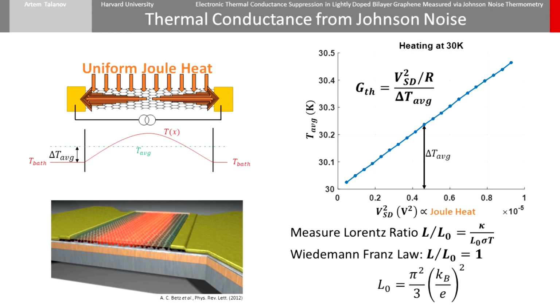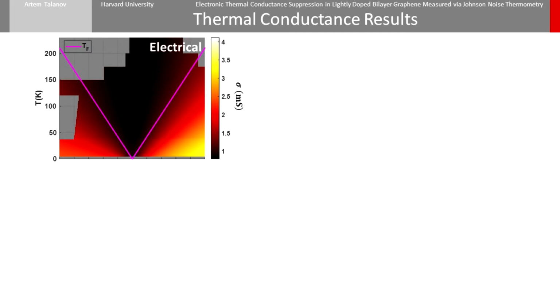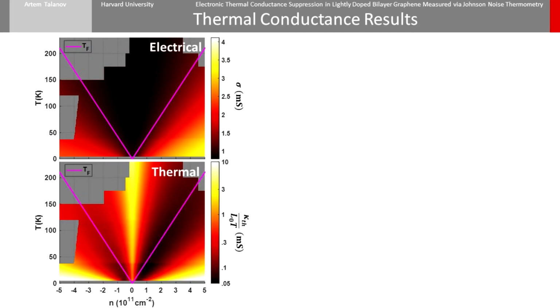In analyzing our data, we compute the Lorentz ratio and compare it to the Wiedemann-Franz law, where the Lorentz ratio is defined as 1. Here I present the results of my measurements. The top panel shows electrical conductivity versus density and temperature, and the bottom panel shows thermal conductivity normalized to the same units as electrical conductivity, but note that I am now plotting it on a log scale as it varies over many orders of magnitude. This is the raw data.